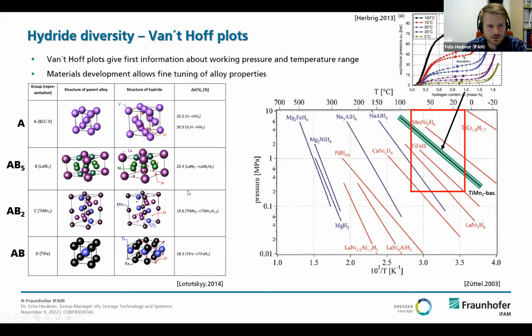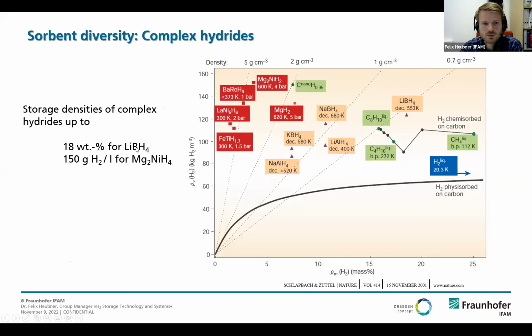The metal hydride family often has a very, very high volumetric storage density, but you always need the host metal to carry the hydrogen. That means the gravimetric storage density is sometimes low, so these conventional interstitial hydrides are not used for mobile applications. They are more used for stationary applications, and there's a lot of research going on in the field of complex hydrides.